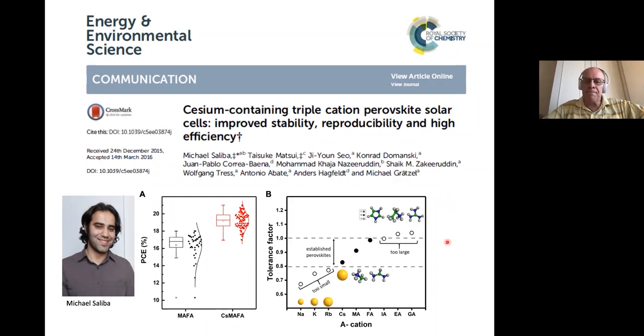So to continue the compositional engineering, one has to look into the size of the ions, and you can calculate something called the tolerance factor. It's a geometrical formula, basically, with the radius of the ions. You can see here that if you take methyl ammonium, it falls in the window where you can form the perovskite structure. It should be between 0.8 and 1 to form the perovskite structure, the cubic alpha phase, as we call it. If you go to formamidinium, it's a little bit on the larger side, cesium a little bit on the smaller, but the combination of them makes a very good quality, as I said. If you go further, rubidium is a little bit small here, and so on. But there are certainly others you can try.